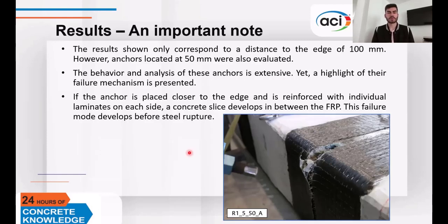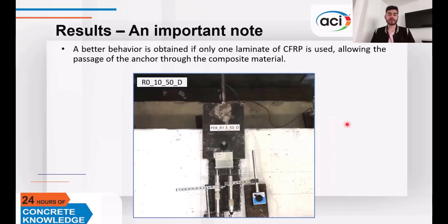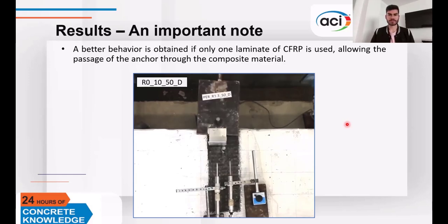Lastly, an important note. The results I previously showed you corresponded to anchors located 100 millimeters from the border. However, for 50 millimeters anchors, some aspects of their behavior were similar and some of them were different. But what I wanted to tell you is that when the anchor is placed really close to the edge and the reinforcement consists of individual laminates on each side, then a concrete slice forms between the FRP sheets. This failure mode limits the capacity of the system, as steel rupture is not achieved. Better behavior is obtained if just one laminate is used, allowing the passage of the anchor through the fiber, as we see in the video. In this specimen, we obtained steel rupture.